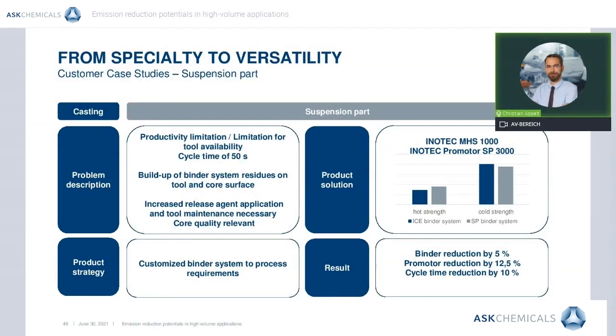The second example arises from the field of suspension part casting. The customer reported a limitation in productivity due to long cycle times and a reduced tool availability in the core shop. The current addition rate of the inorganic binder system was in principle too high, but necessary to handle the voluminous cores because of strength. The buildup of binder system residues on the core box surface and the core itself resulted in excessive use of release agent and tool maintenance work in short intervals.